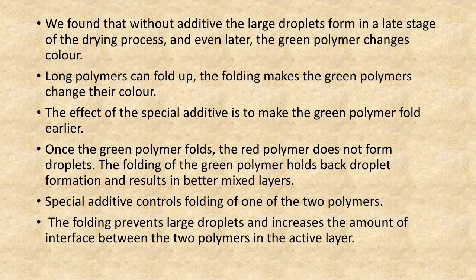The green polymer changes color. We have to stop the changing of the green polymer. Thus, we know that long polymers can fold up, and folding can make the green polymer change its color. The effect of the special additive is to make the green polymer fold earlier. When the green polymer folds, the red polymer doesn't form droplets, and as a result it can be mixed better in the layer.